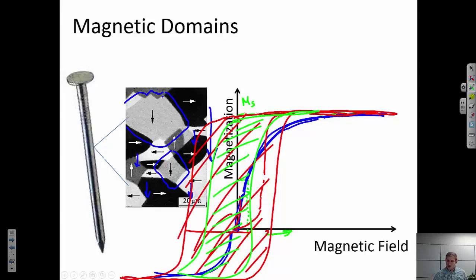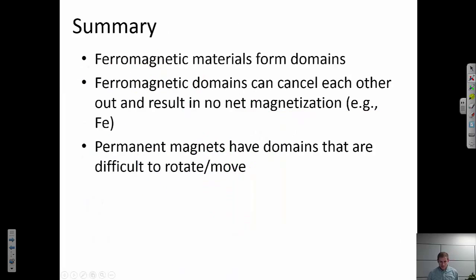So this is kind of at the heart of it, but the thing that I want you to remember the most here is that all of this magnetization behavior on the bulk level is caused by the reorientation of the different domains on the microscopic level. Again, this is sort of micron level, and if I was able to zoom way, way in, I could again see all these atoms that within a domain were all arranged in the same direction.